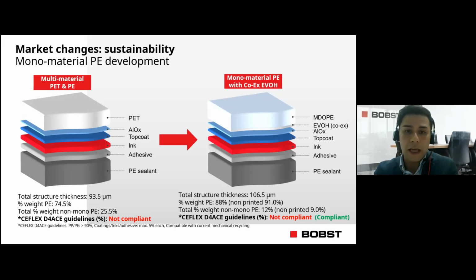Even though PET is chemically a fantastic material, which offers exceptional barrier properties against oxygen, and on its own as PET bottles and jars is actually a preferred material for recycling due to its lower carbon footprint compared with glass or aluminium, in a flexible packaging structure, it does not lend itself to mechanical recycling due to its need to be sealed with LDPE. PET, generally speaking, as a sealing layer, has poor sealing performance characteristics, although there is ongoing research on PET to improve sealability, but it is not widely commercial today.